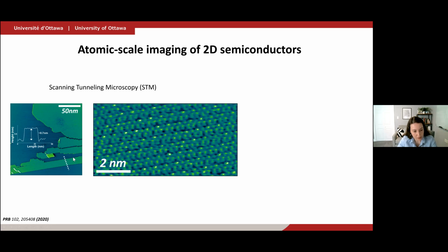And the fact that you see these lines across the surface, and we measure the thickness, they're really one atom thick structures. And the fact that they're aligned in these directions also tells us something about the symmetry of this material. In this case, it's an in-plane anisotropic material. As we zoom into the surface, we are also able to see the individual atoms, as you see in this image here, where we also find that they're organized in rows of atoms in such an in-plane anisotropic 2D semiconductor.